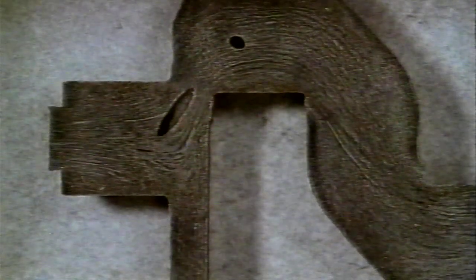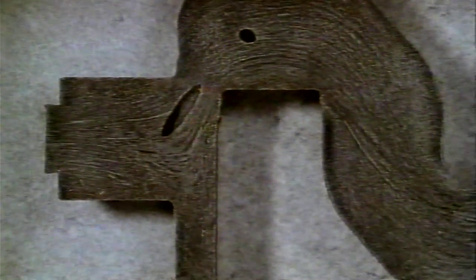A major advantage of forging is the form and texture produced in the component. We have sectioned and etched this forged crankshaft so that we can see the forming texture. A forming texture typically has two components, a crystallographic texture and a fibre texture. The crystallographic texture involves preferred orientation of the grains within the component and is difficult to image directly. What is revealed by etching here is the fibre texture.